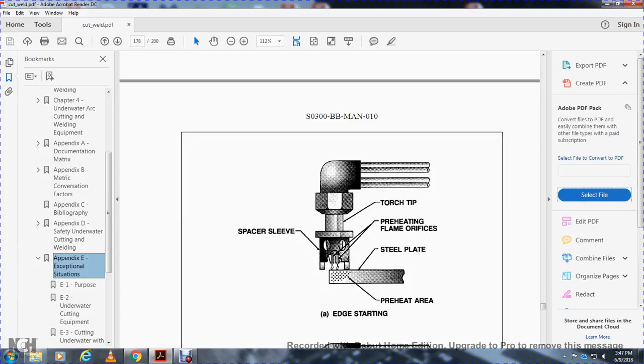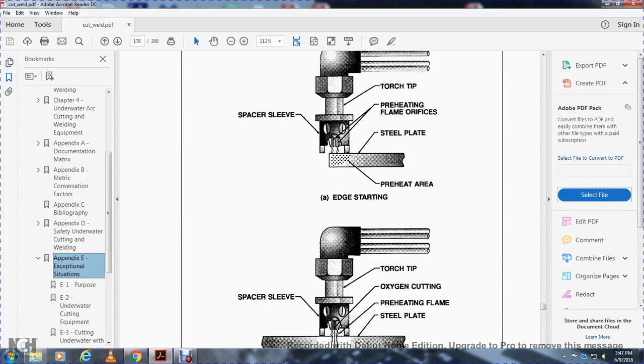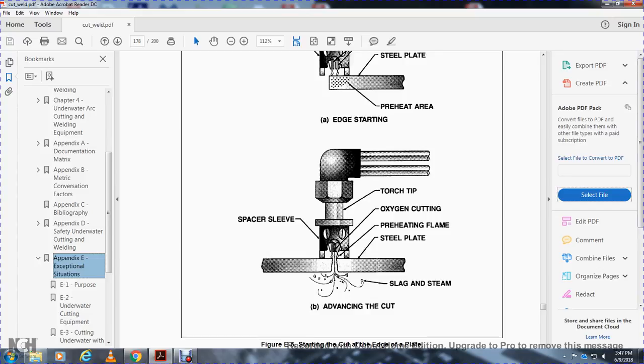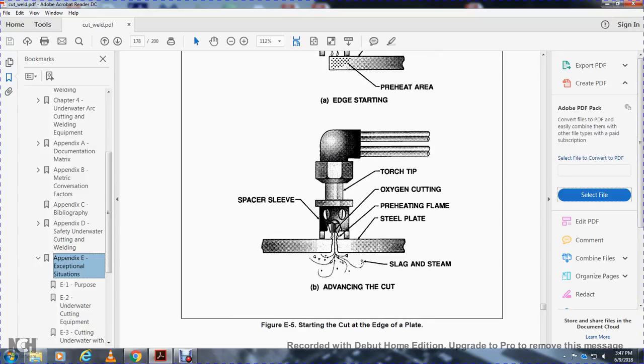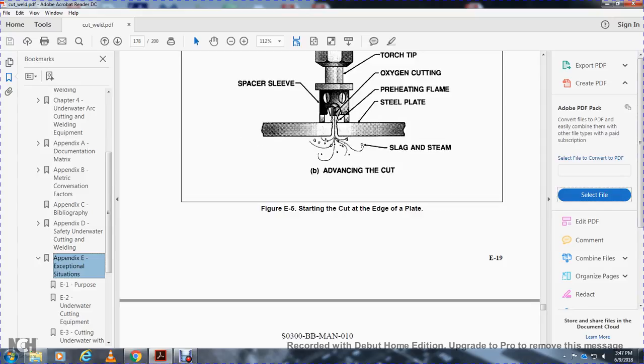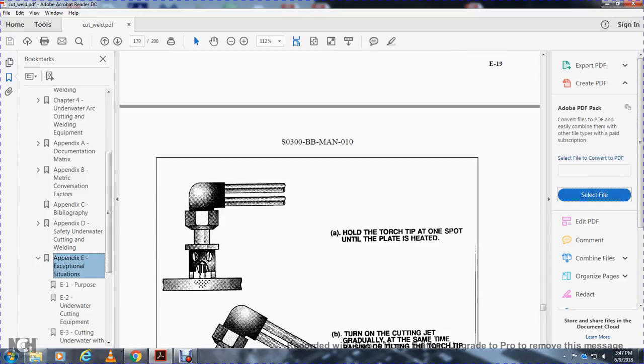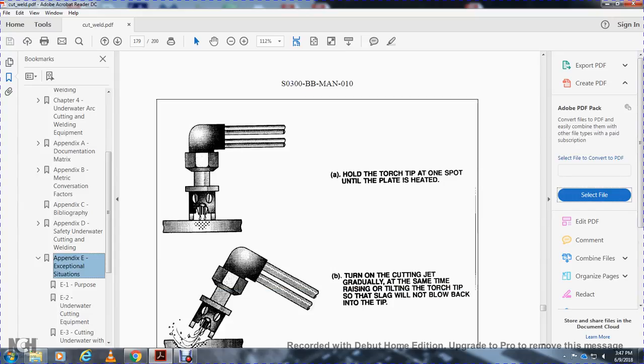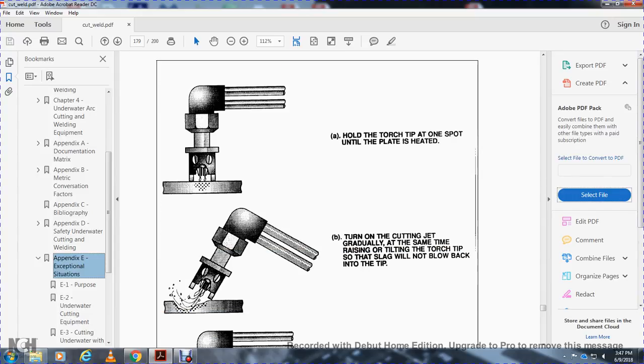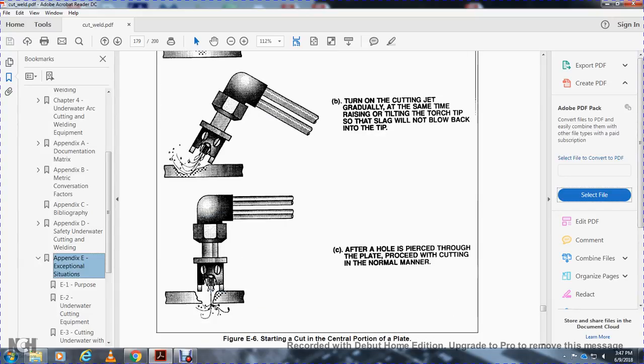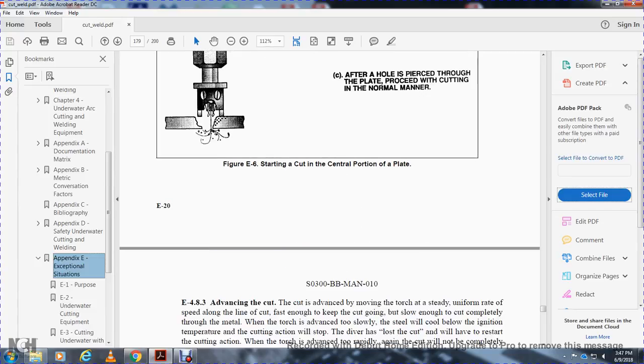This shows the torch head, preheating flame orifice, the steel plate, the spacer sleeve, and the preheated area. The torch head, oxygen cutting jet, spacer sleeve, preheating flame, steel plate, slag, and steam advancing in the cut, starting the cut with the edge of the plate. A, hold the torch with the tip at one spot until the plate is heated. B, turn on the cutting jet gradually while tilting and raising the torch so that the slag will not blow back into the tip. C, after the hole is pierced through the plate, proceed with the cutting in the normal manner.